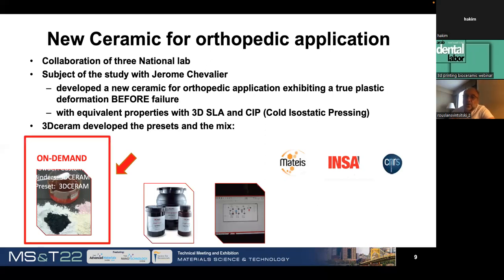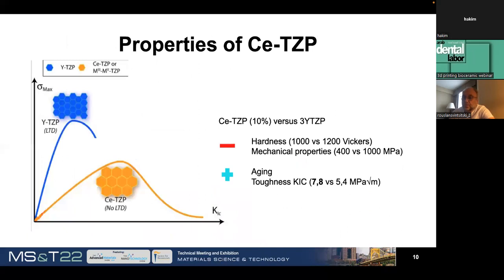So this project was implemented in the frame of on-demand service, and it took about, let's say, 12 months to do this job with all the tests performed by Matthias. First, when we identified this cerium-doped zirconia, we could find that the strength of the material was very low compared to the yttria zirconia. Yes, we won in toughness, as you can see on this diagram. Strength is the Y axis, and toughness is X. So it's toughness in relation with strength.